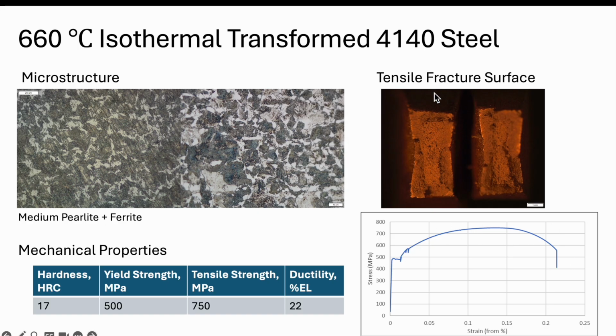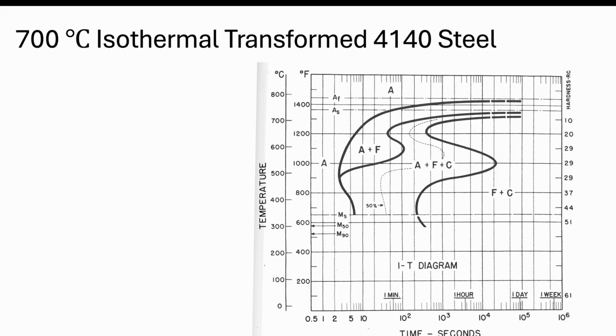So from the fractured surface of the tensile sample, again, we see a change in shape, smaller than the original cross-sectional diameter. And the area here is not very flat, which indicates the ductility. So we see less and less of the brittle part, and it becomes a lot higher change of area here as it becomes more ductile. So we've got one more to look at, and that is the 700.